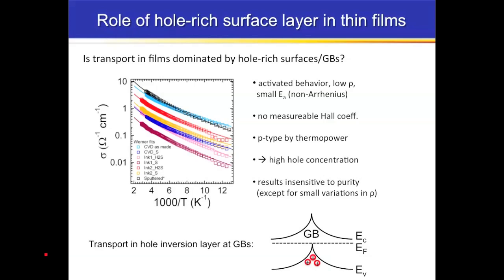If you look at the behavior of thin film pyrite materials, this is conductivity versus temperature now, no matter how we make them, they basically fall in the same kind of behavior, right? There's a spread in the overall conductivity, but this could be due to measurement error, who knows? The important thing is that they're all curved in the same way, they have about the same activation energy. No matter whether we make them by CVD, molecular ink, or if we even look at other people's data, like made by sputtering, it's pretty much all the same. And remember, this is all P-type by thermopower, high hole concentration, low mobility.